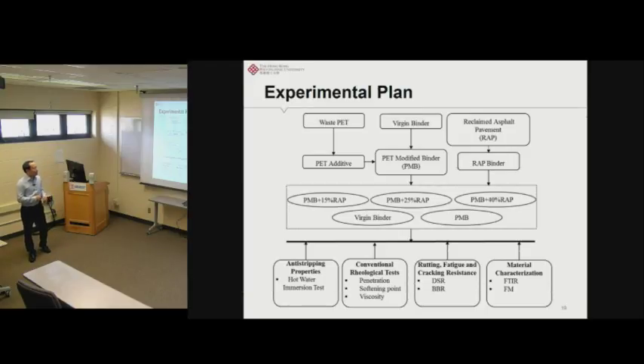So what we have done is first we collect the waste plastic or waste PET, and then we use the aminolysis process to convert it into the PET additive. And also we collected the virgin binder, which is a binder with a penetration grade of 60-70, which actually corresponds to a PG grade of PG64. It's a binder without any polymer modification. And then we can produce the PET modified binder called PMB. So here P represents PET, not polymer.